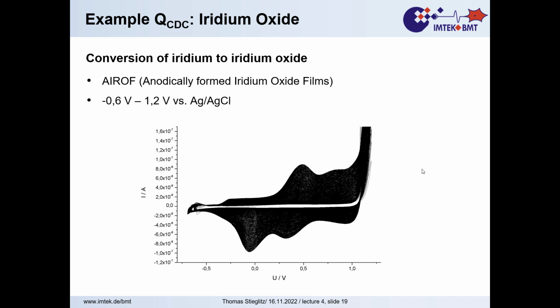And if you imagine you have a bulk material, it grows something on top, and that part flakes off, then you have lost already part of your bulk material. And if you redo that several times, it's like corrosion at the end. You have no bulk material left. And that was one of the reasons why that anodically formed iridium oxide was at one point of time no longer in fashion, because of those hazards.